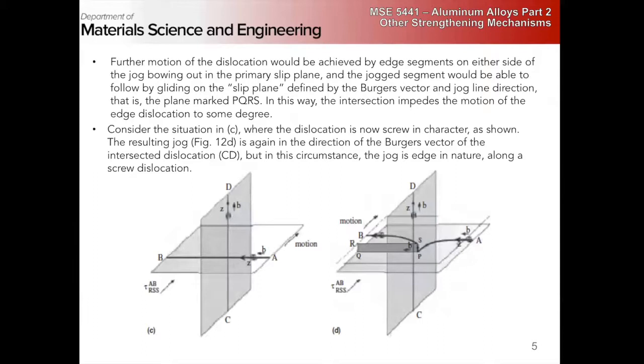Here we have a dislocation that cuts through the slip plane. We call those forest dislocations. If it lies in the slip plane that you're moving on and it's sessile, they just call it parallel dislocations. Two different parallel dislocations give rise to a backstress term. Forest dislocations give rise to work hardening.